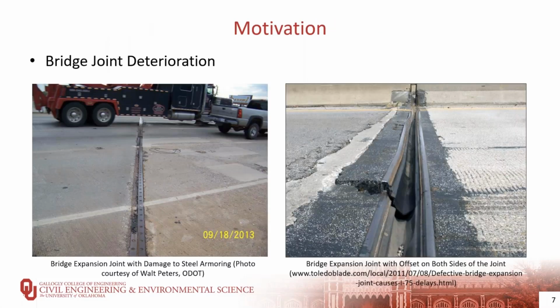This specific project was at least partly motivated by experiences in Oklahoma related to bridge deck joint deterioration, similar to what we show in these pictures, where damage is incurred to the joint armoring, which leads to failure of the joint sealant and allows water to pass through the joint and onto the beam ends. In fact, the first project that Oklahoma sponsored related to UHPC research was related to deteriorating bridge deck joints. So you might say, why does that matter for the pre-stressed girders?